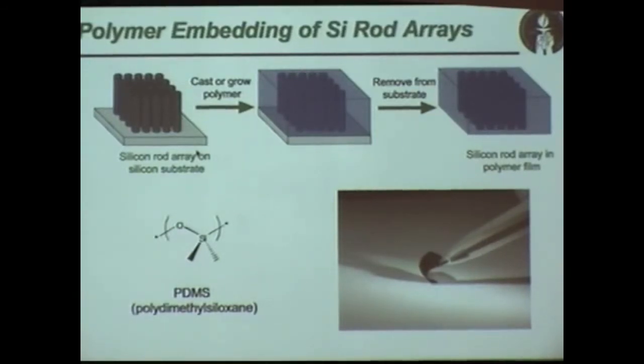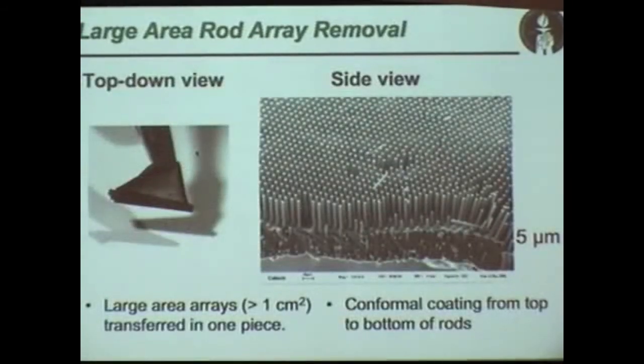piece of plastic. When we do this with a polymer that actually has enough monomer in it that it'll evaporate, we can control the thickness of that. And what we're left behind with is there's the polymer, there are the rods. These are all single crystals of silicon over large areas. This rolls up, you can unroll it. There's almost no load on those rods, so they don't fracture, they don't break.